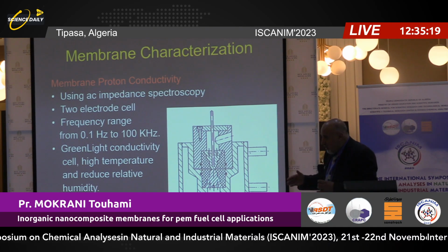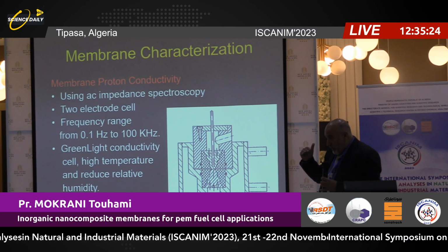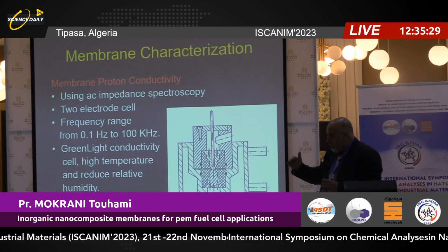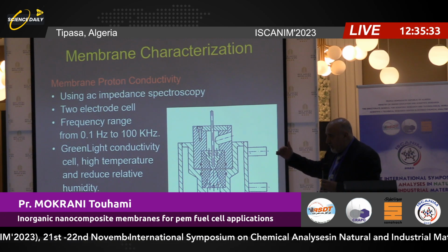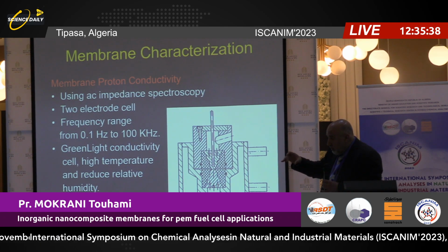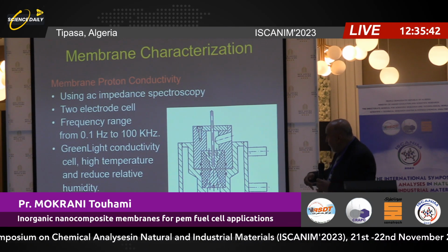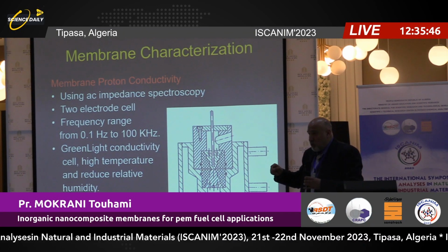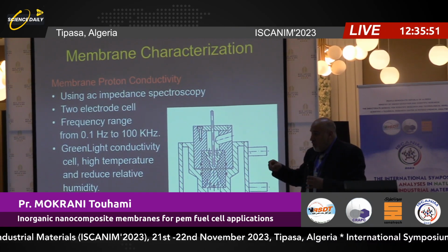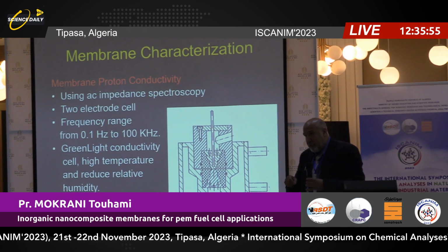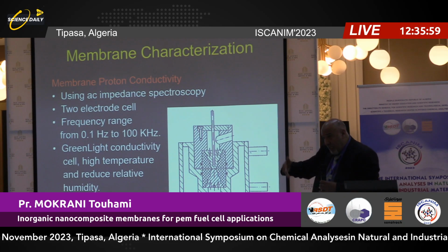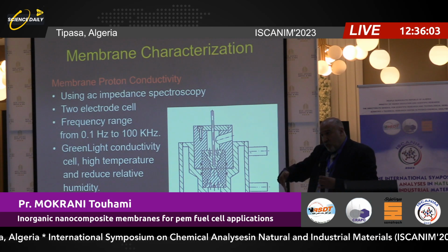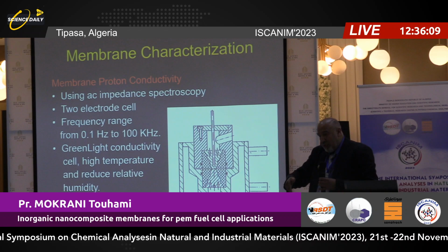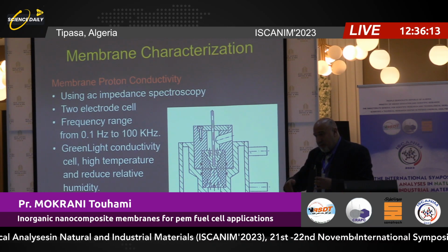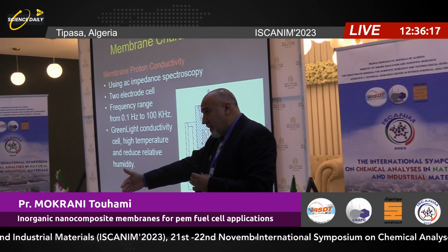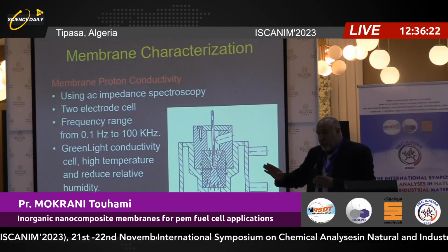Let's say methanol oxidation. Methanol oxidation is a very sluggish reaction. But with pristine Nafion, it's 90 degrees. That's the maximum you can go. But if you work at 120 or 140, mostly 140 degrees, the catalyst is working much better than at 90 degrees. That's one. For the electrode also, it's very nice to work at high temperature, because if you work at, let's say, 140 degrees, you can use reformed hydrogen. What does reformed hydrogen mean? You take methanol and reform it to hydrogen. The problem with the reforming is you get CO. You cannot remove the CO. So you need a CO-tolerant catalyst, because platinum as it is is not CO tolerant. If you inject hydrogen with CO, the CO will poison the catalyst. But at 140 degrees, you don't worry about CO.